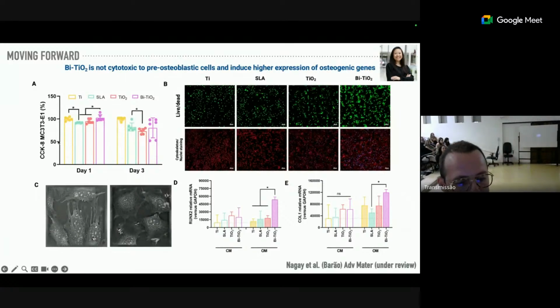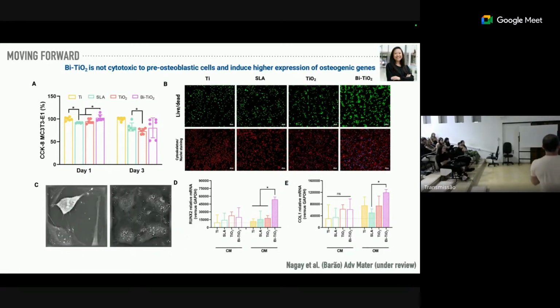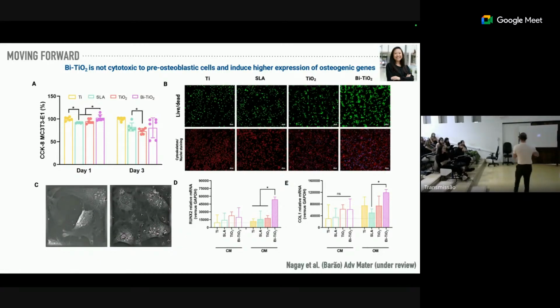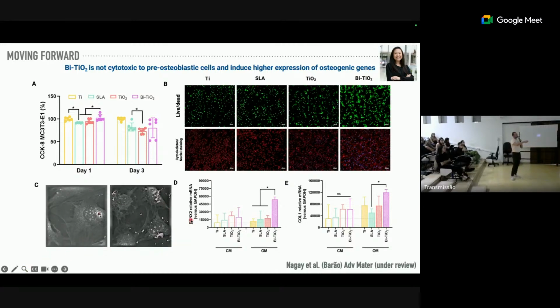So as you can see here, the CCK8 using preosteoblastic cells doesn't show any negative effect. We also have this live/dead exposure of these cells to bismuth, and it seems that they are pretty similar when you compare the control without bismuth and the bismuth in the cell culture. We also investigated some gene expressions, RUNX2 and collagen type 1. We observe a greater content of RUNX2 and collagen for bismuth.